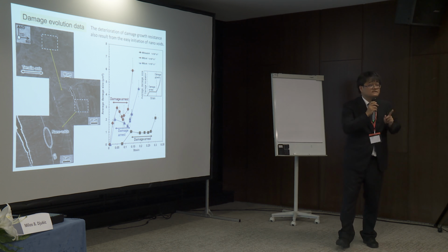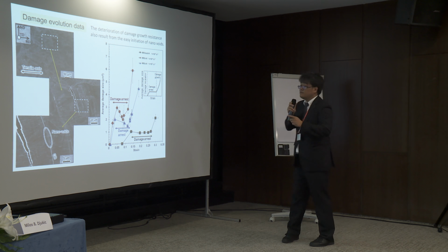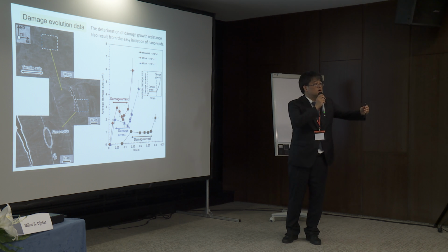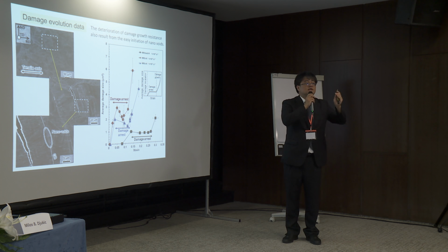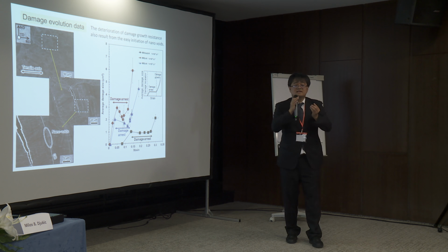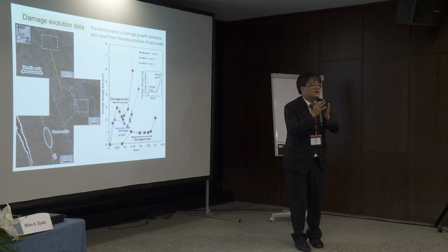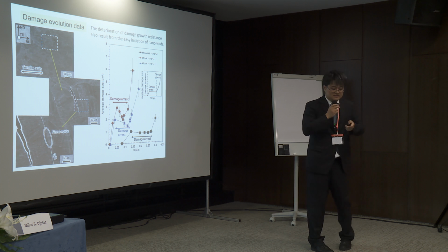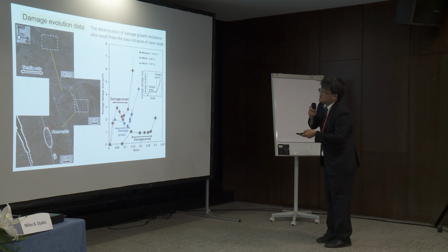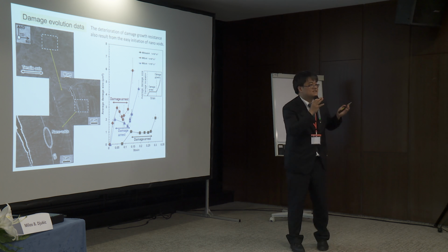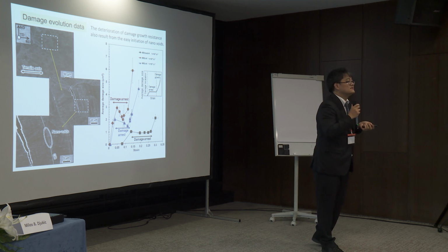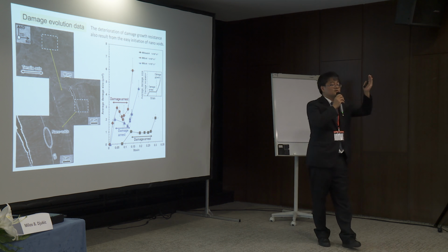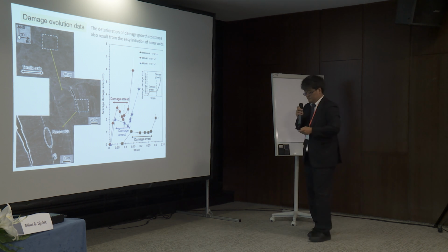Therefore, this is a very important point. Even for the damage growth, the hydrogen-assisted damage initiation, meaning nanovoid formation, controls the damage growth. Always when the deformation or stress level is severe, for example particularly at the crack tip, such nanovoids form. It is a bit self-evident because when the situation is severe, numerous martensite forms. Then with increasing martensite fraction, damage is easily formed.